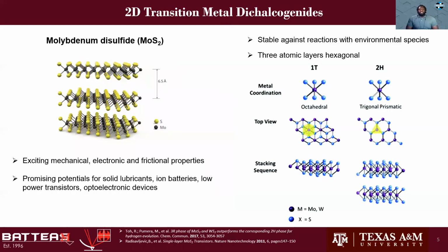And our next 2D material of interest is molybdenum disulfide, and it's in the family of transition metal dichalcogenides. In contrast to graphene, a monolayer of MoS2 consists of an atomic plane of molybdenum atoms sandwiched between two planes of sulfur atoms. Interestingly, there exist two phases of MoS2 that only differ by slight rotations of the bottom sulfur atoms, 1T and the more stable 2H phase. And this slight change in structure yields quite different properties, with the 1T phase being metallic. And in general, MoS2 has remarkable properties that lend towards its application in electronics and as a solid lubricant.